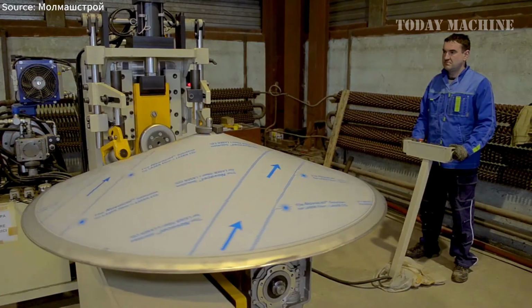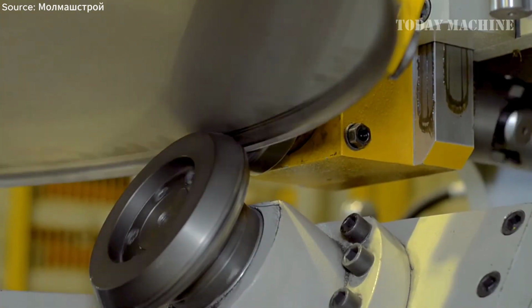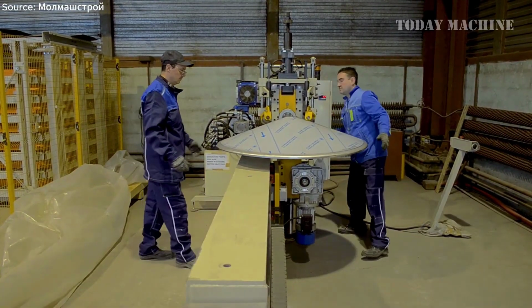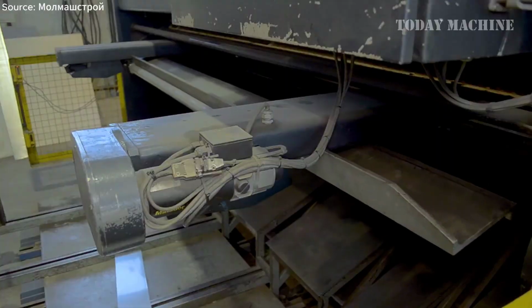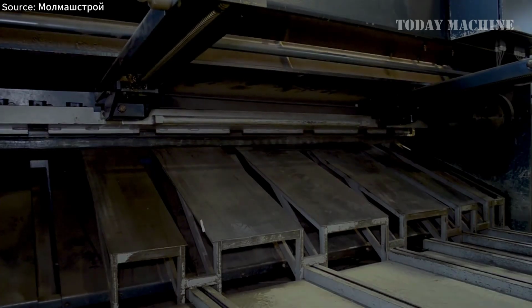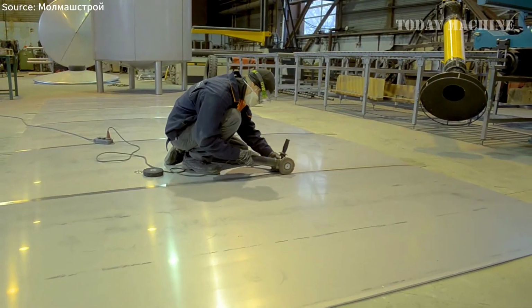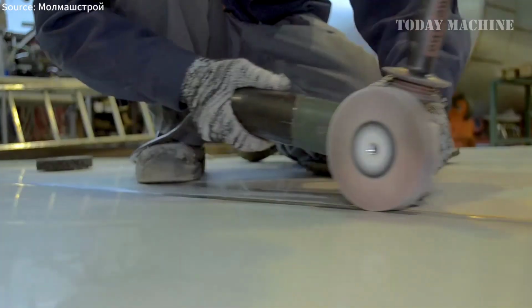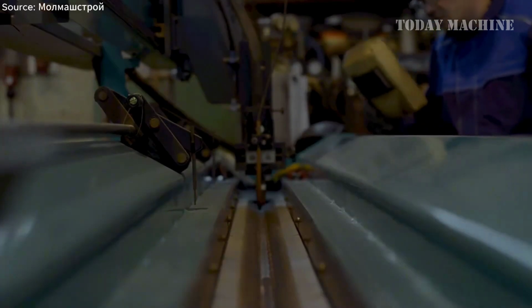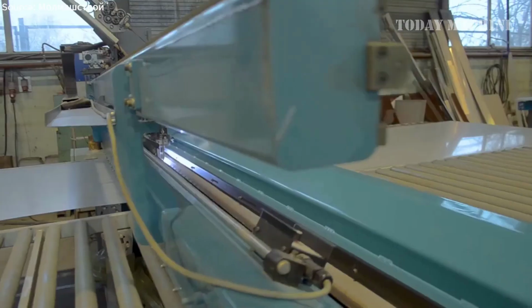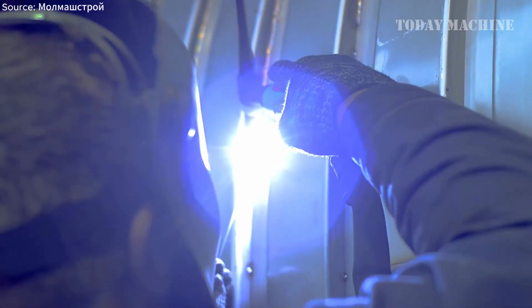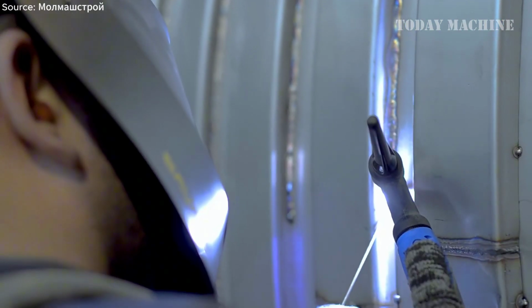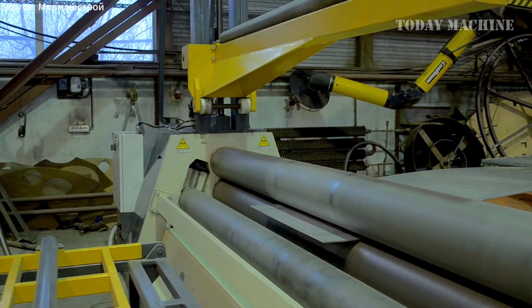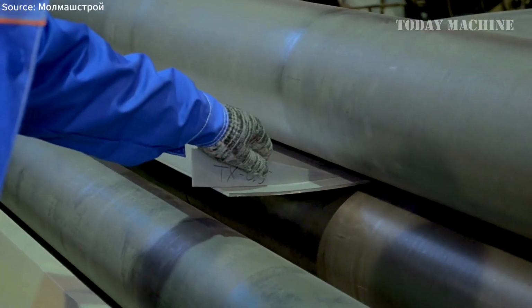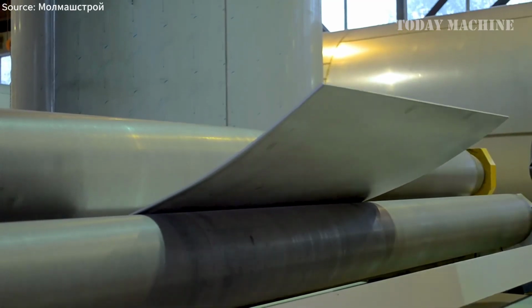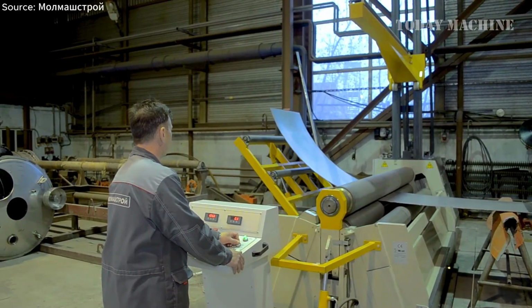Stainless steel tank production begins with laser cutting AISI 304 and 316 L sheets to exact dimensions, ensuring precision in every component. Conical bottoms, up to 5,000 millimeters in diameter, are formed using hydraulic presses for uniform shaping. Automated TIG welding with controlled parameters creates seamless joints, followed by multi-stage grinding and polishing to achieve a surface roughness of 0.8 micrometers Ra. Tanks undergo rigorous hydrostatic pressure and helium leak tests to verify structural integrity.